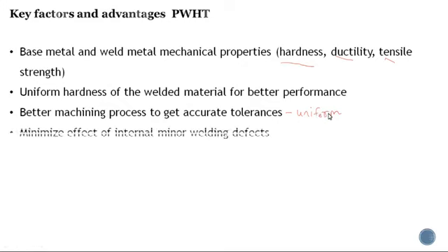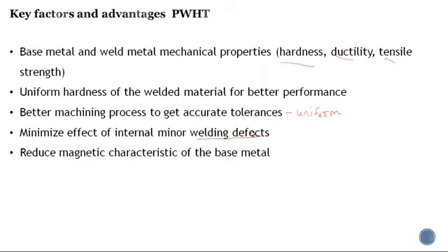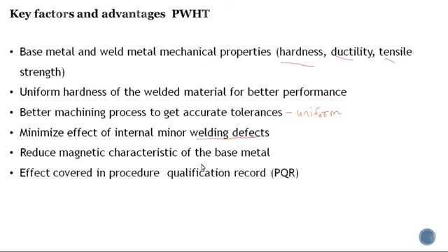This is a very important thing. It minimizes the effect of minor welding defects. There are some residual stresses, and if there are welding defects inside the metal, they are more threatening compared to defects without residual stresses. And finally, the results which we are able to achieve after post-weld heat treatment are mentioned in the PQR, that is your procedure qualification record, and based on that you can judge whether to change parameters and values to improve your welding quality. Thank you.